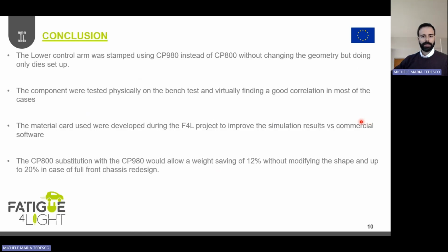So we can conclude that during the Fatigue4Light project we were able to stamp the lower control arm using the advanced high-strength steel, the CP980, instead of CP800, without changing the geometry, but just doing a proper setup of the die. The components were tested physically and virtually, and the correlation between real life and the simulation was very, very good. We were able to predict in most of the cases the correct starting of the crack, and also in some cases the number of cycles.